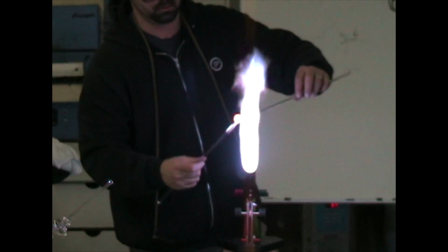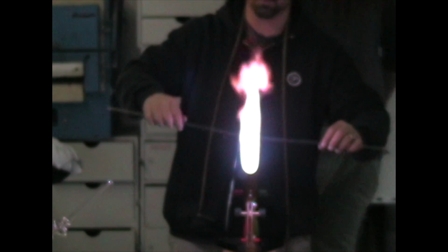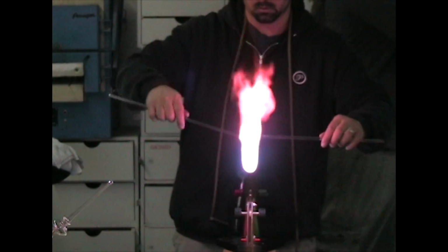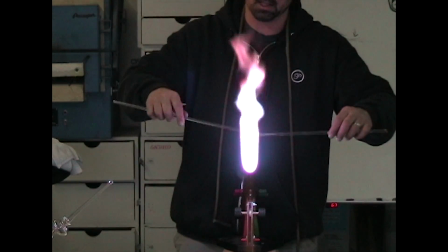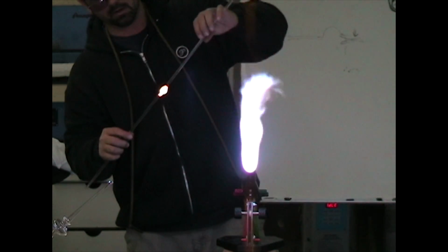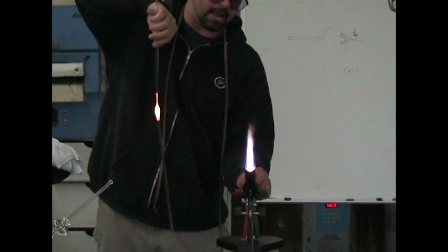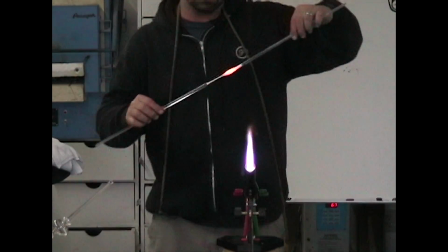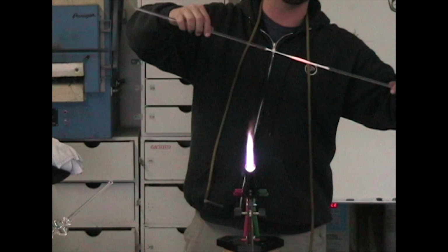So when you stack your stuff together, do you go through all this, like repull all the color down? No, not for a stick stack. Only stuff that's going to be exposed to the surface, like blowouts, or if I'm sculpting with it. If it's a color that has a lot of air in it, it will affect your stick stack, but I kind of avoid those for stick stacks. I will just mix them down and do different stuff with them.